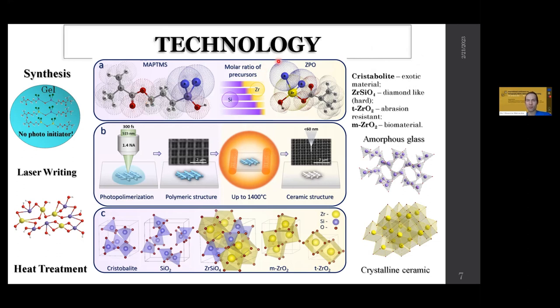So the other slide is just summarizing the technique that we just described, as Maria mentioned, we can tune the initial properties, the composition of a material, which will in turn result in different properties of a 3D printed object after laser writing and developing, and eventually in the material composition after performing the calcination. I would like to stress that the achievable resolution with calcination can be increased further and reach below 100 nanometers without any specific material optimization or beam shaping techniques like STED or others, just by reduction of the volume of the features while keeping its shape. So we can achieve amorphous glass or even crystalline ceramic substances and keep the shape.